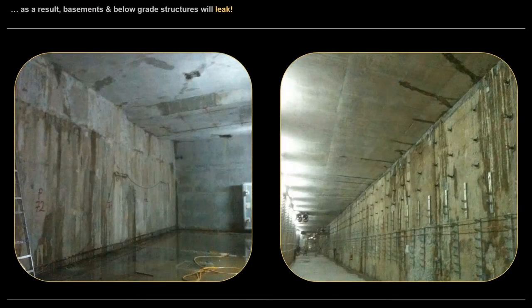Okay, water ingress into tunnels. The picture here on the left is a chamber which has been waterproofed by membranes, and you can see there's various leaks, quite a big puddle of water on the floor there. The problem is with the membrane, it is on the back of that wall. There is no way of knowing where the leak is coming from, but it's finding holes and cracks to come out of and is causing chaos inside that structure.